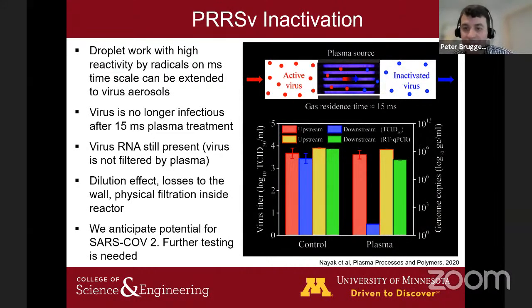And so, motivated by these studies on droplets, where we could decompose a lot of the droplets in a few milliseconds, we built a reactor, put it in a wind tunnel, and we were able to show that plasma is able, if you send the gas stream through the plasma for a contact time here of 15 milliseconds, to fully inactivate the virus. And what you see here, this is the blue curve before and after. This is a log scale. So we have like 3 log reduction. And actually the remaining half log is the detection limit. So we cannot find any viable virus.